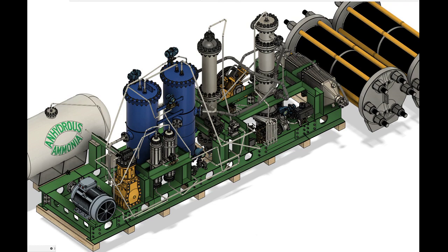Data from a book on high-temperature corrosion of metals, the nitriding rates are plotted for various componentry of typical Topsoe-style ammonia converters. The highest nitriding rate is found in the lining of the main converter vessel, with a corrosion rate of 9.8 mils per year. The lowest corrosion rate is found in the wire meshes and inner shell, where a nitriding rate of 0.04 and 0.4 mils per year is experienced. These figures are taken from the book, High Temperature Corrosion and Materials Applications, by George Lai.